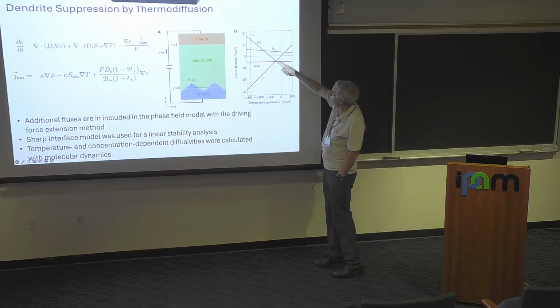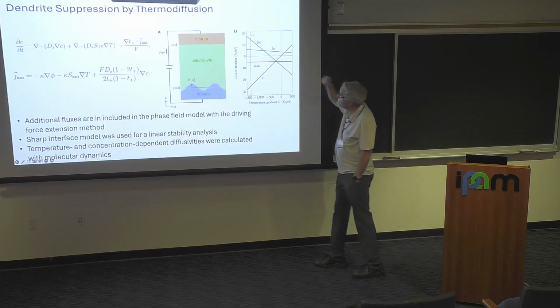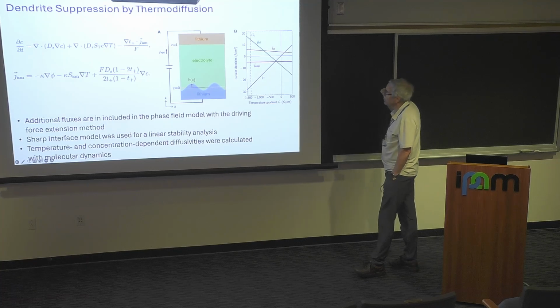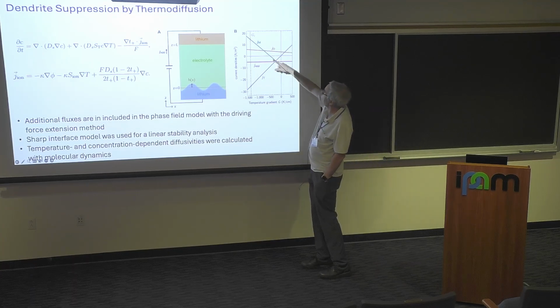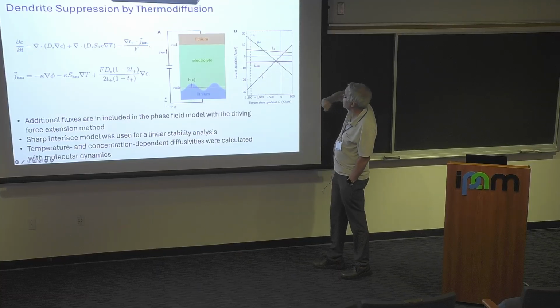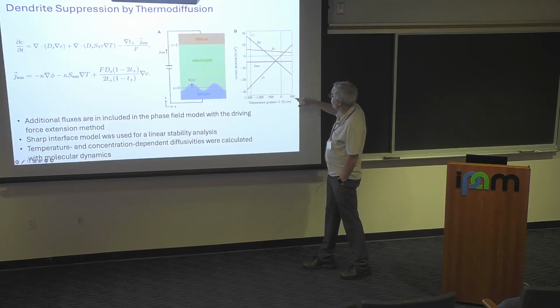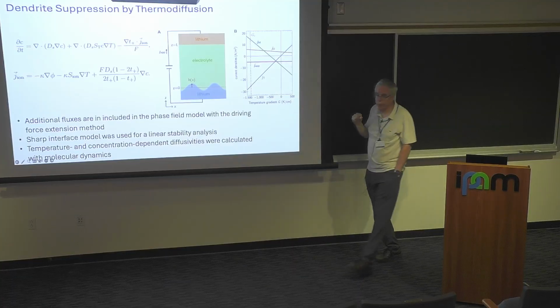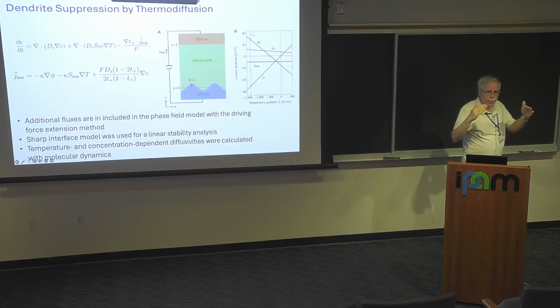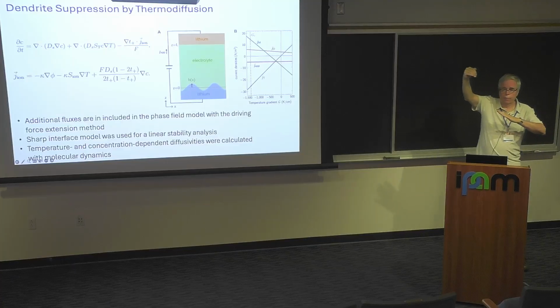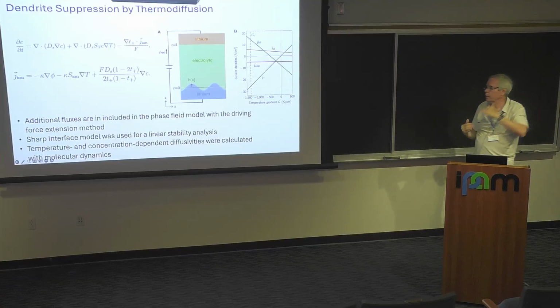And you can see that this flux due to the thermally generated, to the temperature gradients, is on the same scale as what you would see for the migration. It's kind of even on the same scale as the diffusive case. And in fact, it changes sign as you change the temperature gradient. And so it matters whether the temperature gradient is positive, negative anode cathode, or negative positive anode cathode.